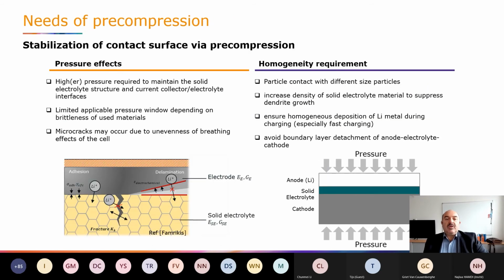The solid structure of the electrolyte also brings some troubles ahead. Due to this mechanical structure, the surface properties of electrodes and electrolyte require a high pressure on the cell, so that the electrical contact is good enough to ensure a proper movement of the ions during the medium. But there must not be too much pressure on the materials due to their brittleness and the behavior of the material under the breathing conditions mentioned before. Microcracks could occur and damage the cell permanently.